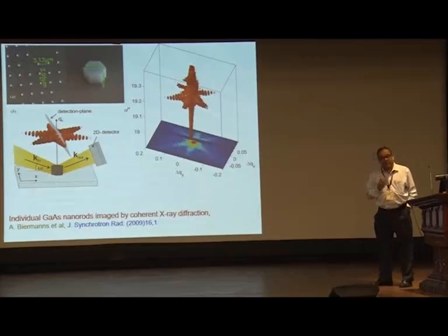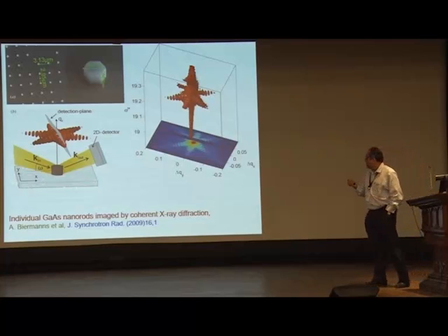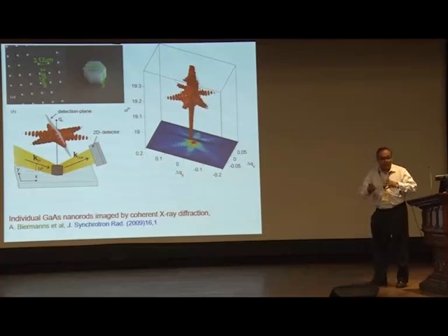That's the technologically important material. Then the X-ray actually goes through, because very little scattering will happen from such a tiny object, and that's the problem. The second problem is engineering: how to hold the beam on the tiny dot when you are doing the measurement, because there is thermal vibration.